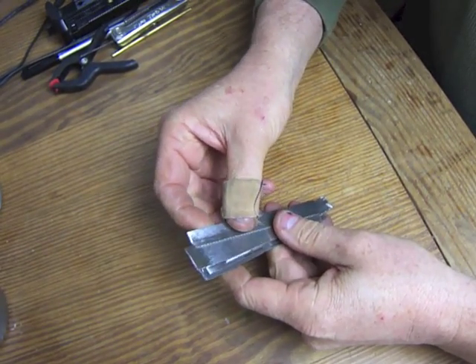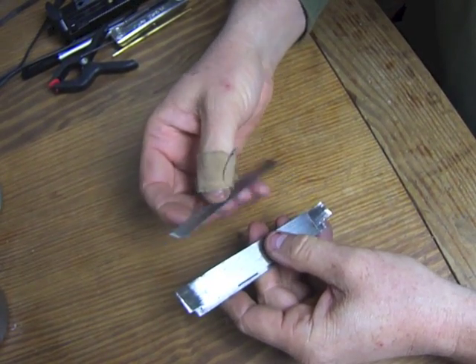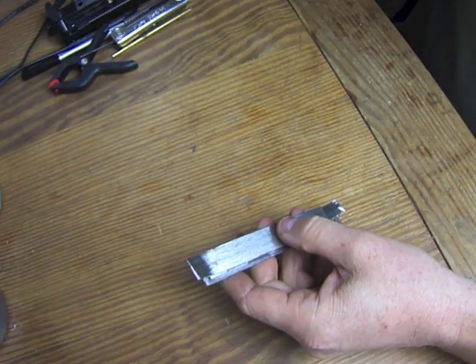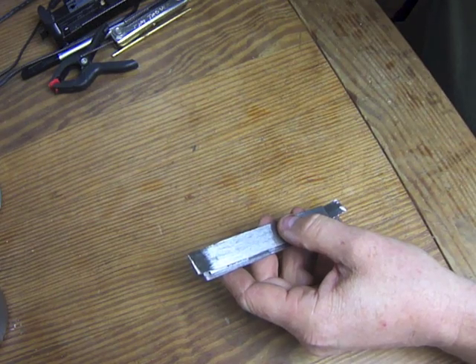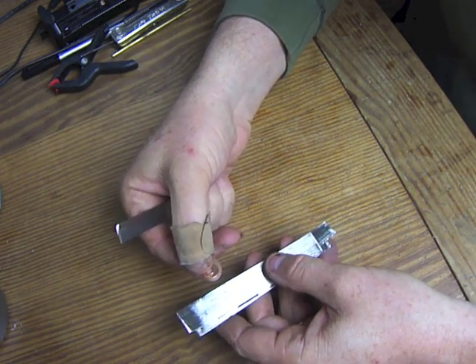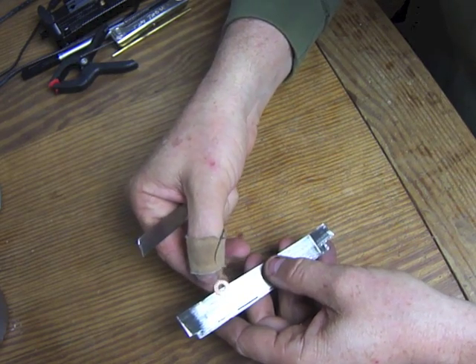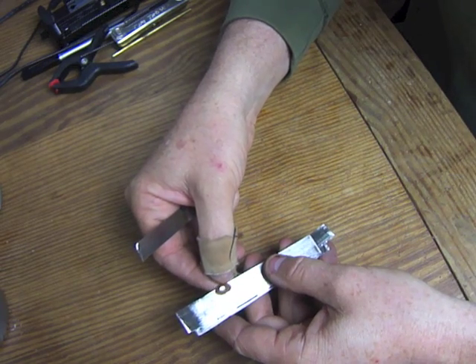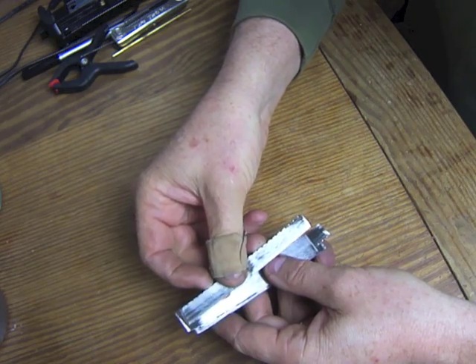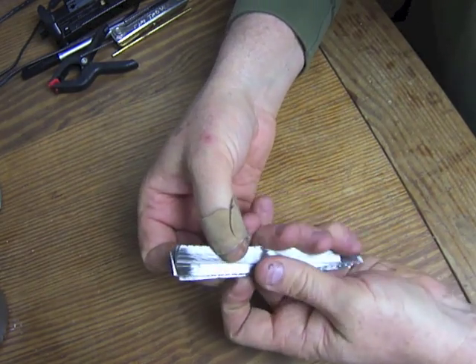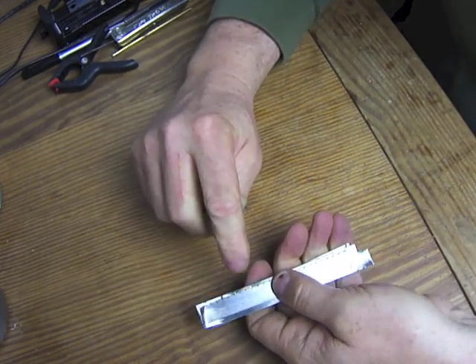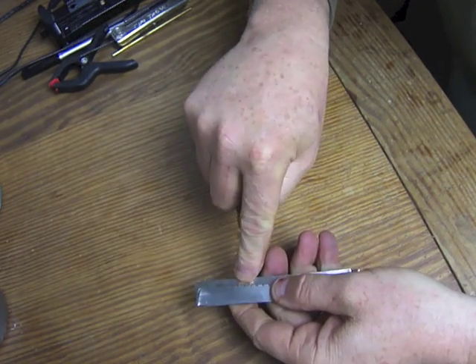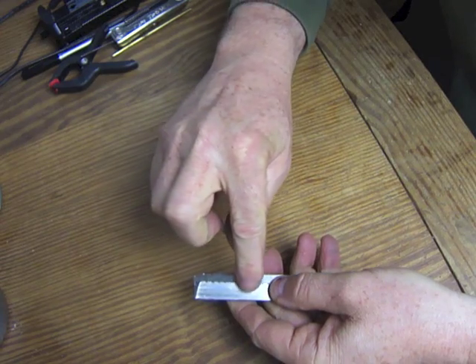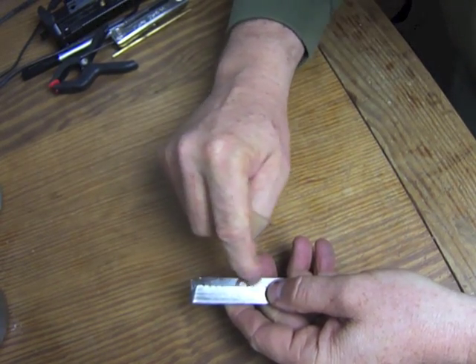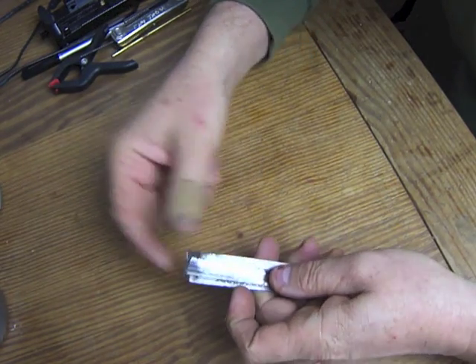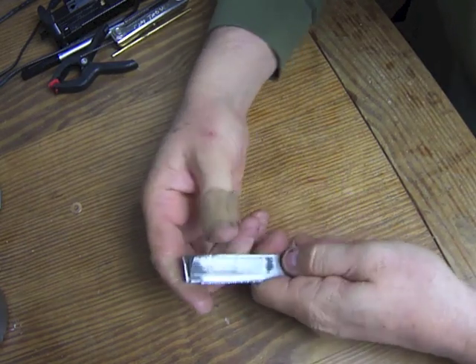In other words, one of the troubles with forging in coal is, you can imagine, let's say, for instance, this little washer here represents some dust from the coal, or some impurities from the coal that get in between your steel. And you can imagine if you weld this up, right there where that inclusion is going to be an area, when you grind through that it's just black and it cakes out, and then you have a divot in your steel. So keeping the steel really clean, and that's why propane also is a big advantage for forging.